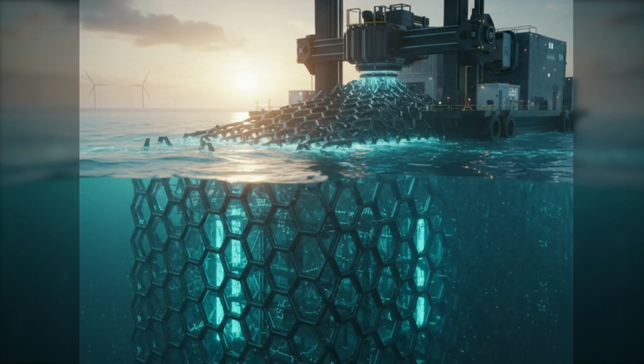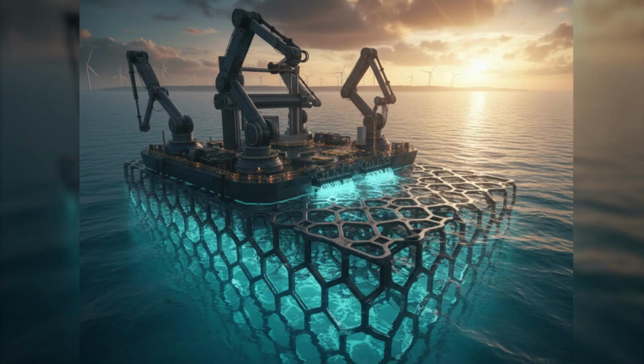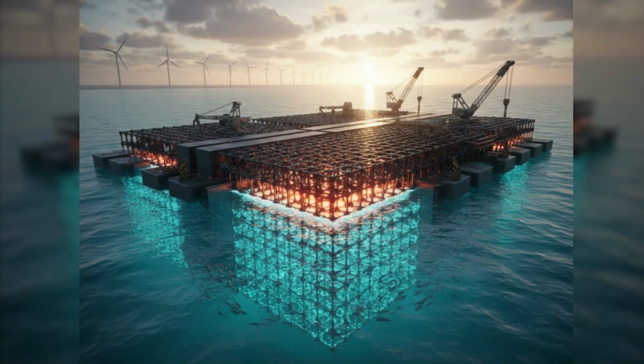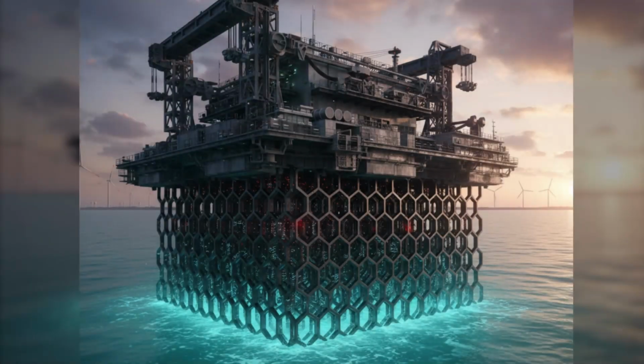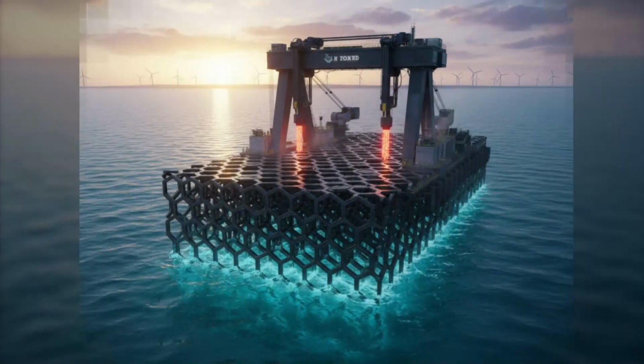Because 3D printed metal inherently has microscopic air pockets or voids inside it, right? Since it's built layer by layer. Exactly. And if you put a porous valve onto a submarine experiencing deep sea pressure, it's going to implode. That internal porosity is exactly why Step 5 requires a furnace for hot isostatic pressing, or HIP. Okay, what does that do? The part is placed in a chamber flooded with argon gas and subjected to extreme heat and intense pressure simultaneously. This essentially squishes the metal from all sides. It squishes the voids shut. Exactly, crushing those microscopic voids shut and making the titanium fully dense.